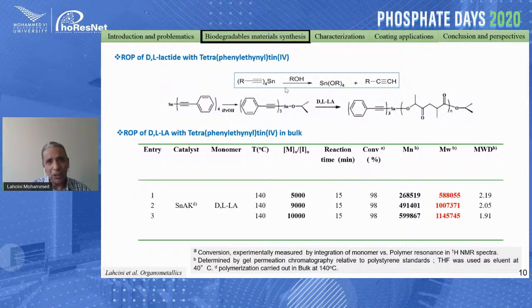With the same aim, to develop a really simple catalyst to prepare high molecular weight polymer, we investigated this tin(IV) compound. As we previously showed, this compound leads to tin oxide by reaction with water, and to tin alkoxide by reaction with alcohol. We tested this complex with alcohol to polymerize the lactide in the same conditions as before, and we observed really good control of the polymerization.